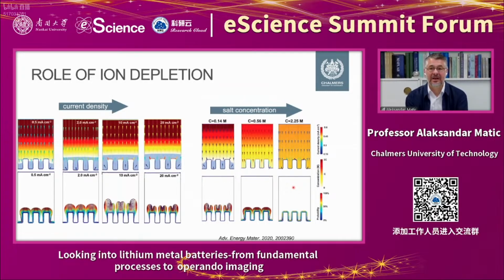So in simulations, you can vary the conditions as much as you like. Here's one of the results that we obtained where we could vary either current density or salt concentration. Here we went from really low currents, 0.5 milliamps per square centimeter, to super high currents of 20 milliamps per square centimeter, something that you might not achieve in reality. And we could see that when you increase the current, you enhance the formation of a very heterogeneous and porous morphology.